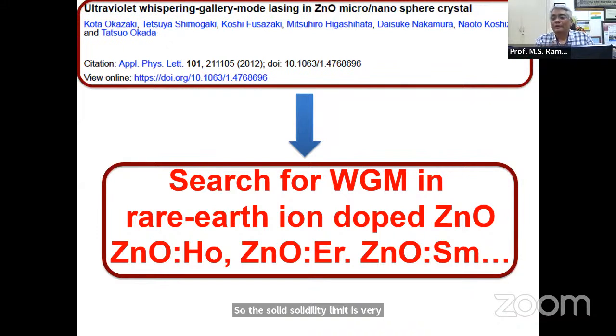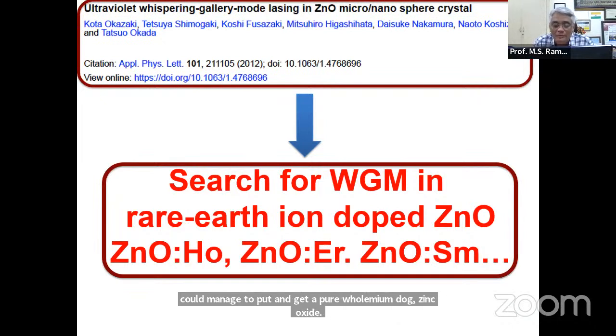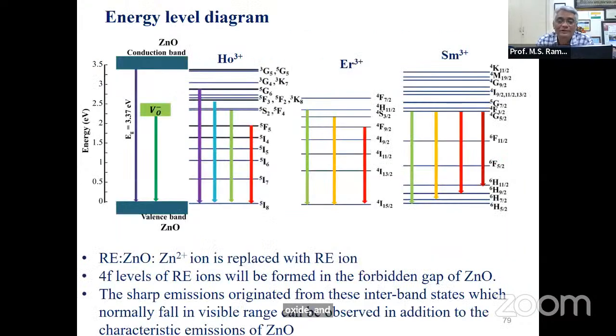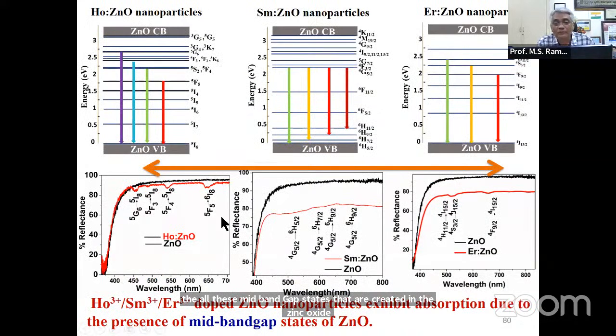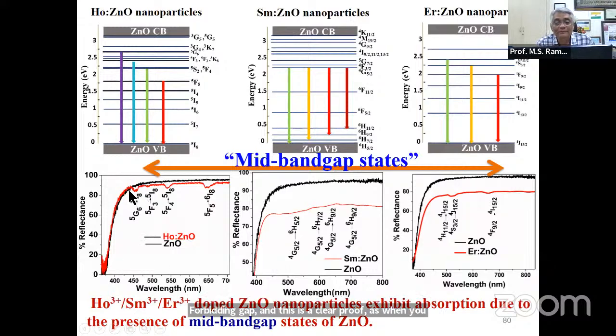But we could manage to get pure holmium doped zinc oxide and other rare earth ion doped zinc oxide at very low concentrations, not more than 1 atomic percent. That was sufficient for us to exploit all these mid-band gap states created in the zinc oxide forbidden gap. This is clear proof - when you do a simple absorption or reflectance versus wavelength measurement, you clearly see the presence of these mid-band gaps.